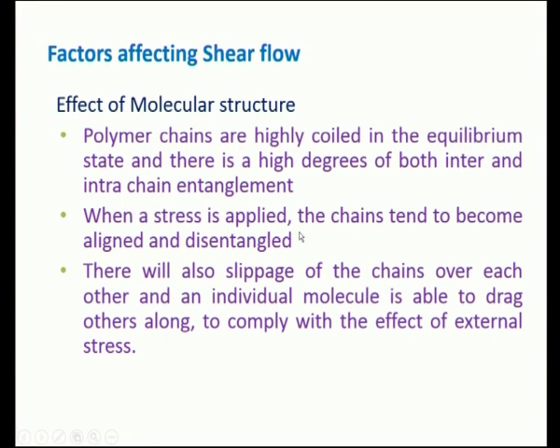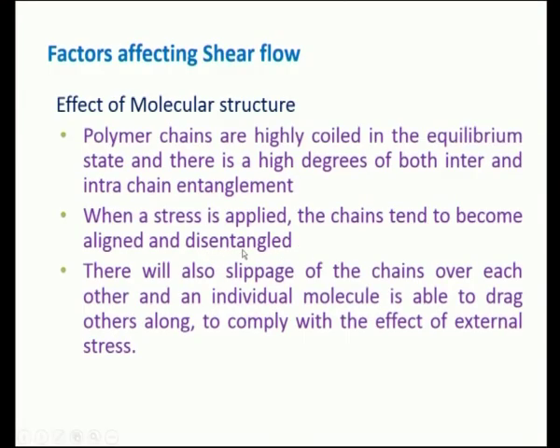Now when a stress is applied, the chain tends to become aligned and disentangled. Once you apply the stress, it is more or less like a coiled wire. Once you try to uncoil the wire, it may straighten up. The similar case with respect to polymeric chains. Once a stress is applied, these chains tend to become aligned in the direction of application of force, and it gets disentangled. This will facilitate slippage of the chains, that is one chain will slide over another chain, and an individual molecule is able to drag others along because there is no entanglement. One chain when it is attached to another chain, one chain starts moving, the next chain will also move. As a result, with respect to the external stress, there will be an easy flow with respect to the increase in stress.